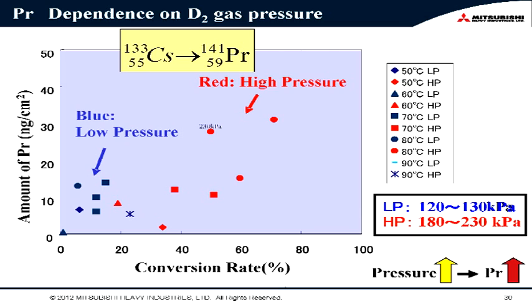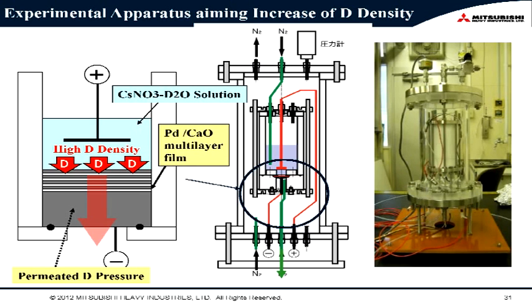And we can see that if we increase the pressure, we get more praseodymium. So D2 pressure is very important for increasing the amount of praseodymium. So we try to increase the praseodymium using the electrochemical method,